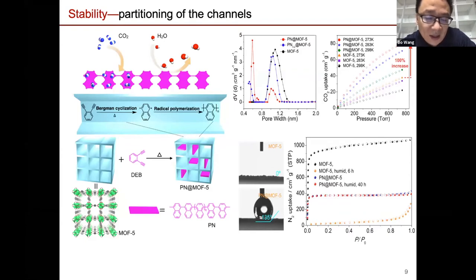We can get a polynaphthalene inside the channel. The reason we picked polynaphthalene is that it's rather rigid. It's not going across those pores in different dimensions. Here, it behaves like a blade. It cuts the channel in half. As you can see from this pore size distribution calculation, upon increasing the polymerization degree, you can cut the pore all the way from 1.1 nanometer to 0.5 nanometer nicely, and it changed dramatically that way. So you polymerize further, you cut the pore in half.